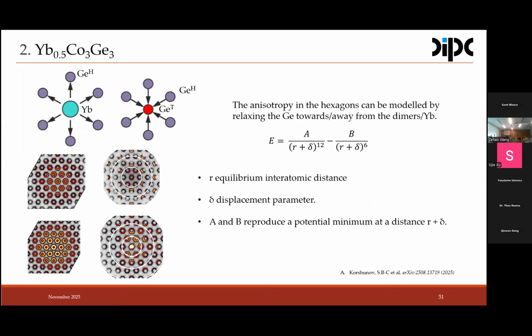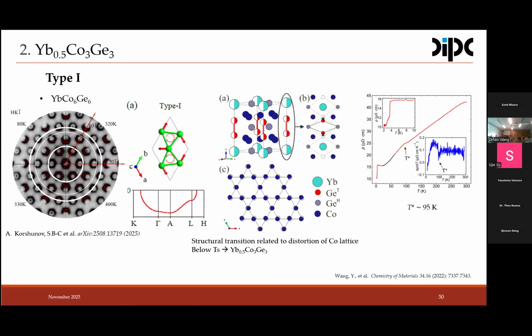Was this also the Monte Carlo simulation? Yeah, it's Monte Carlo. So this is the diffuse scattering without considering only germanium pairs. You see how the diffuse is symmetric. But if you take into account how the ytterbiums and the honeycomb germaniums move in plane, you can perfectly model the hexagonal diffuse scattering like we get here.